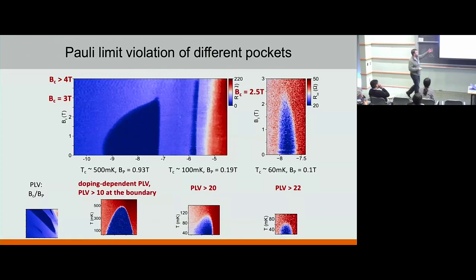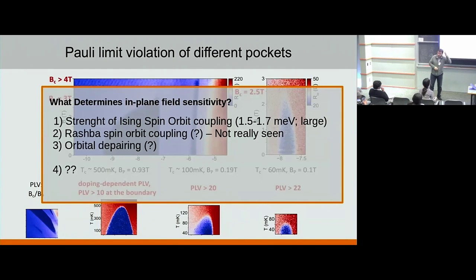So there is something funny happening with these pockets, even if you focus on one pocket itself. So now we can kind of think of what actually determines this Pauli limit violation ratio. If you very naively assume that everything is dominated by Ising spin-orbit coupling, then this Ising spin-orbit coupling gives you some energy range, like 1.5 meV. If you convert that to a magnetic field, you get something around 20 Tesla. So clearly something is different in these pockets that is preventing reaching 20 Tesla, okay?